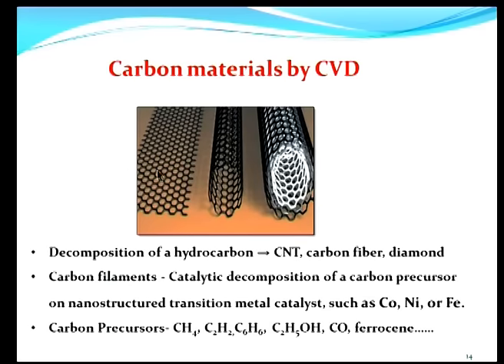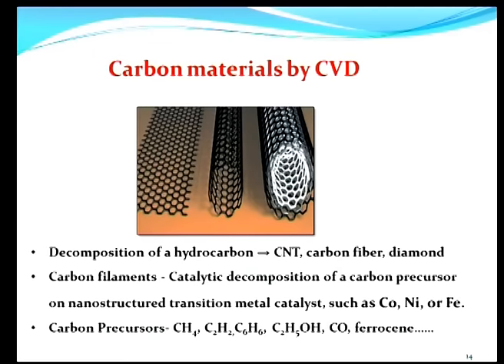The two-dimensional graphite lattice — the graphene sheet — is the template. It turns out that graphene, single-walled carbon nanotubes, and multi-walled carbon nanotubes can all be produced by essentially the same chemical vapor deposition method using a variety of precursors: methane, acetylene, benzene, ethyl alcohol, carbon monoxide, ferrocene, and so on. By slightly altering the methodology for decomposition and catalysis, it is possible to get carbon nanotubes — multi-walled, single-walled — by the general CVD method which works at around 700 to 800 degrees Celsius.